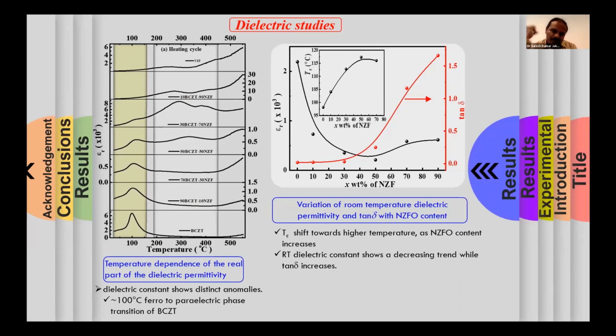Because if we don't have a very separate interface between the magnetic and the piezoelectric phase, what will happen is, because the magnetic phase is conducting, if there is some kind of interdiffusion or any interaction between them, conductivity will increase and we will not get any magnetoelectric response. So that is very important, that we prepare composites with separate interfaces.